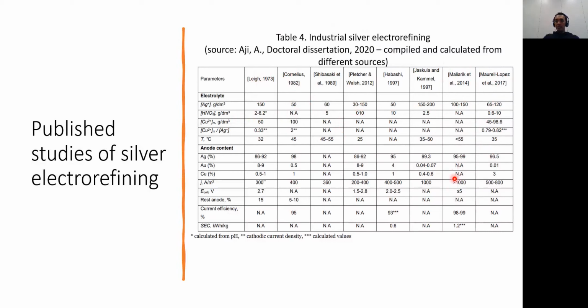This paper by Maliarik is very interesting. So Maliarik worked for Outotec at that time. I think he still works for Outotec. He published this paper, which promotes this high current density process by Outotec. In this publication, he suggests that the current density can go very, very high. So does Kramer, but in Maliarik, it's really motivating to go to higher current density in that process. And it has very low energy consumption and so on. So this is one paper that also motivated me to investigate further this process.